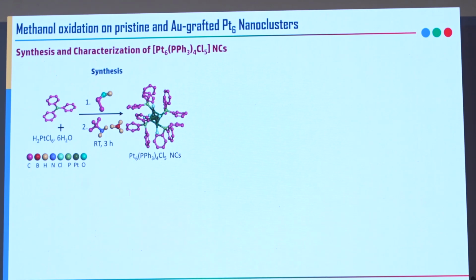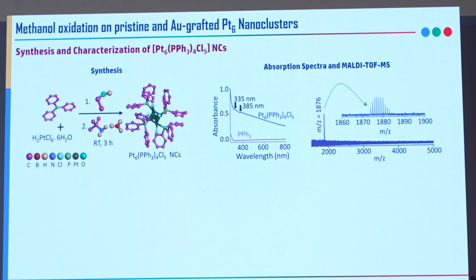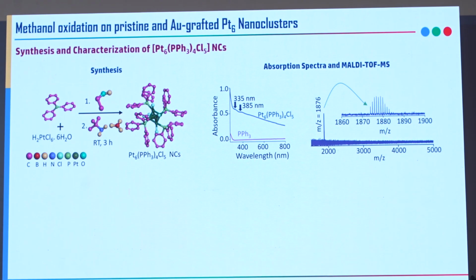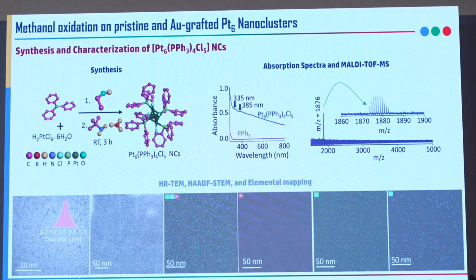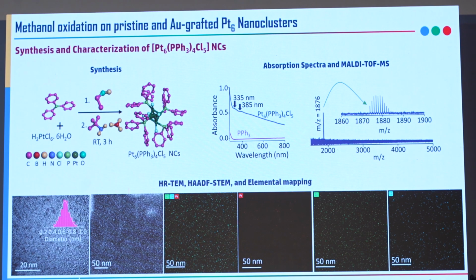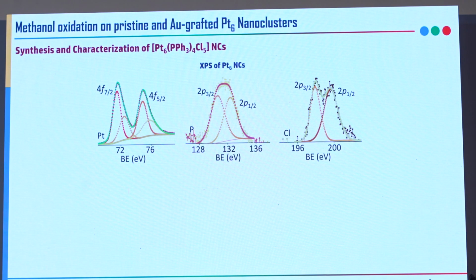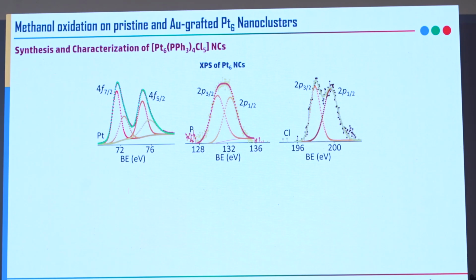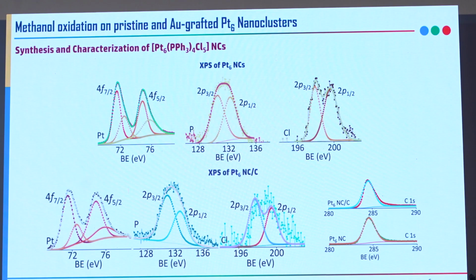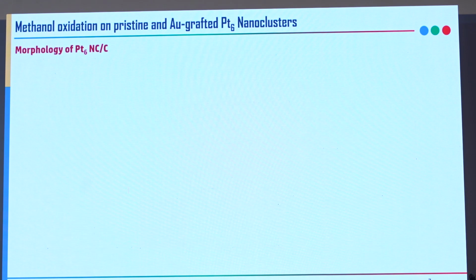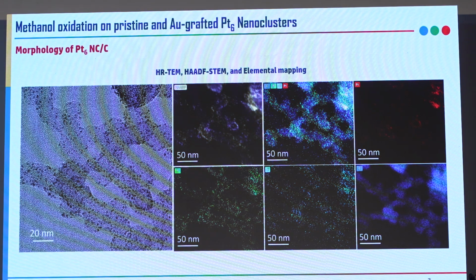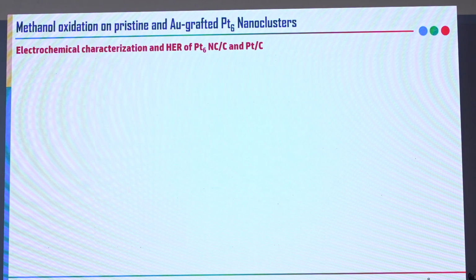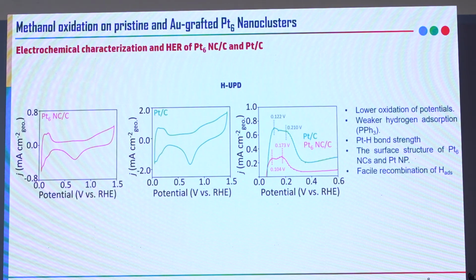using a chemical reduction method, with triphenylphosphine as the ligand. The formation of these nanoclusters was characterized and confirmed using absorption spectra and mass spectrometry, and the size was analyzed using TEM and HAADF-STEM analysis. We also confirmed the bonding in the nanoclusters with XPS analysis. For the electrocatalytic application, we impregnated the platinum 6 nanoclusters into Vulcan carbon, which we again characterized using XPS analysis, and the morphology was also analyzed with TEM analysis. After this preliminary characterization, we used these platinum 6 nanoclusters incorporated into the carbon for electrochemical applications.